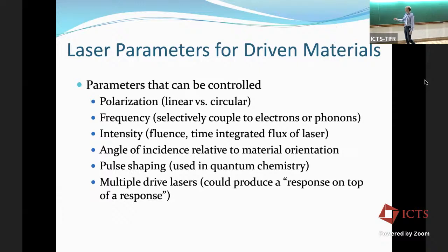The angle of incidence relative to the material orientation, there are matrix elements in how the light's going to couple to phonon or electronic degrees of freedom. And by changing the relative angle of the incident light with the crystallographic directions, then you basically can play with matrix elements and give different material responses, all other things being held equal.